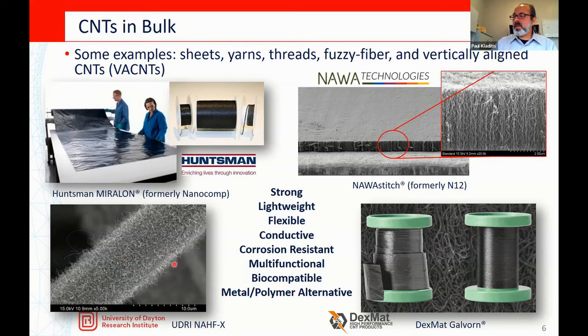And then, because of our expertise in growing, we were able to help another company called N12 initially, and then they eventually were bought by NAWA Technologies in France, and NAWA has established a NAWA America, which makes vertically aligned CNTs. So we use our same reactor that we used to grow carbon nanotubes on carbon fiber cloth. We take in bare substrates and we grow these vertically aligned carbon nanotubes. This is the substrate they're growing on here, and these are the vertically aligned carbon nanotubes.